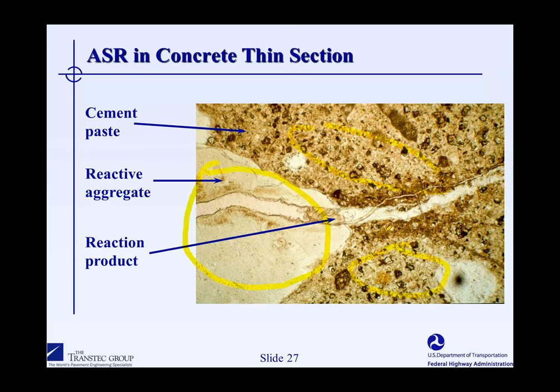The aggregate has expanded and cracked, and you can see a crack running through the aggregate and out into the surrounding cement paste. In certain parts of this crack, you'd see a reaction product. Here's gel inside the crack in the aggregate, and here's gel filling the crack out in the cement paste. We call this a site of expansive reaction. It's evidence that ASR has occurred, and not only that ASR has occurred, but that it has caused distress to the surrounding cement paste. And this is an important symptom to find if you're going to diagnose ASR as the cause of some apparent damage in the structure.